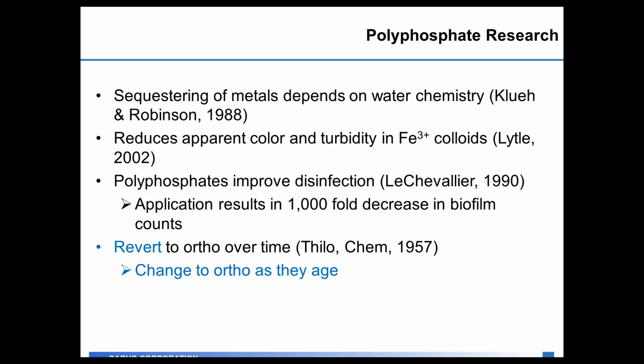Just like with orthophosphate, there's been a lot of polyphosphate research done over the years. That research involves, as simply as, the sequestering of the metals is dependent on what type of water chemistry you have. So looking at the pH of your water, what other things are in the water in addition to the iron and manganese you're trying to sequester. We know that polyphosphate reduces the apparent color and turbidity in iron colloids, so iron is one of the things that's very easy to sequester in the distribution system. There has been additional research that shows polyphosphates help improve disinfection in the distribution system in combination with chlorine. What happens is the polyphosphate helps break up the biofilm in the distribution system, and now your chlorine can more effectively remove the biofilm. The paper by LeChevallier talks about a 1,000-fold decrease in biofilm counts from the combination of polyphosphate with free chlorine versus just free chlorine by itself.